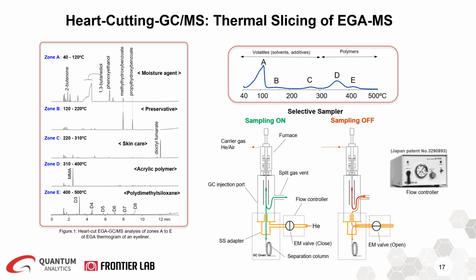On the right-hand side, you can see an EGA thermogram of an eyeliner that can be sliced into 5 different zones or peaks, zone A to E. The heart-cutting technique allows us to program the pyrolyzer furnace into 5 temperature zones in this case, and obtain separate GCMS chromatograms to identify the components in each thermal zone. So the analysis of each thermal zone yields a chromatogram containing only those compounds evolving from the selected range. The figure on the left shows each zone and their corresponding identified components.